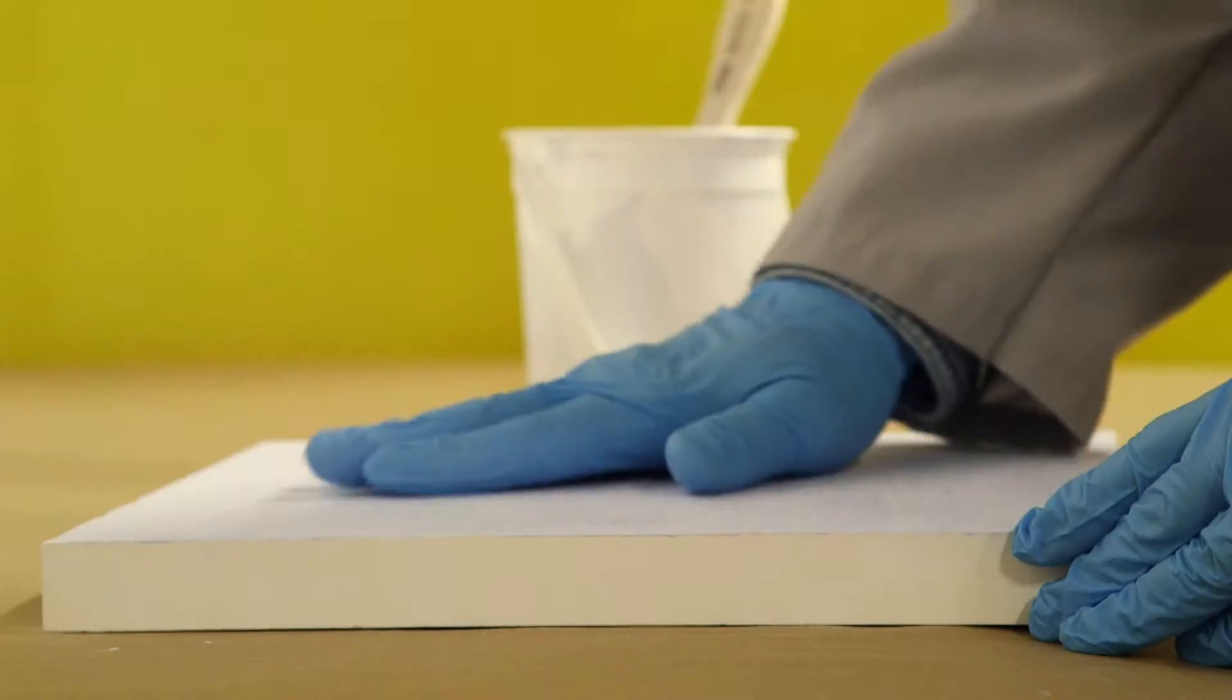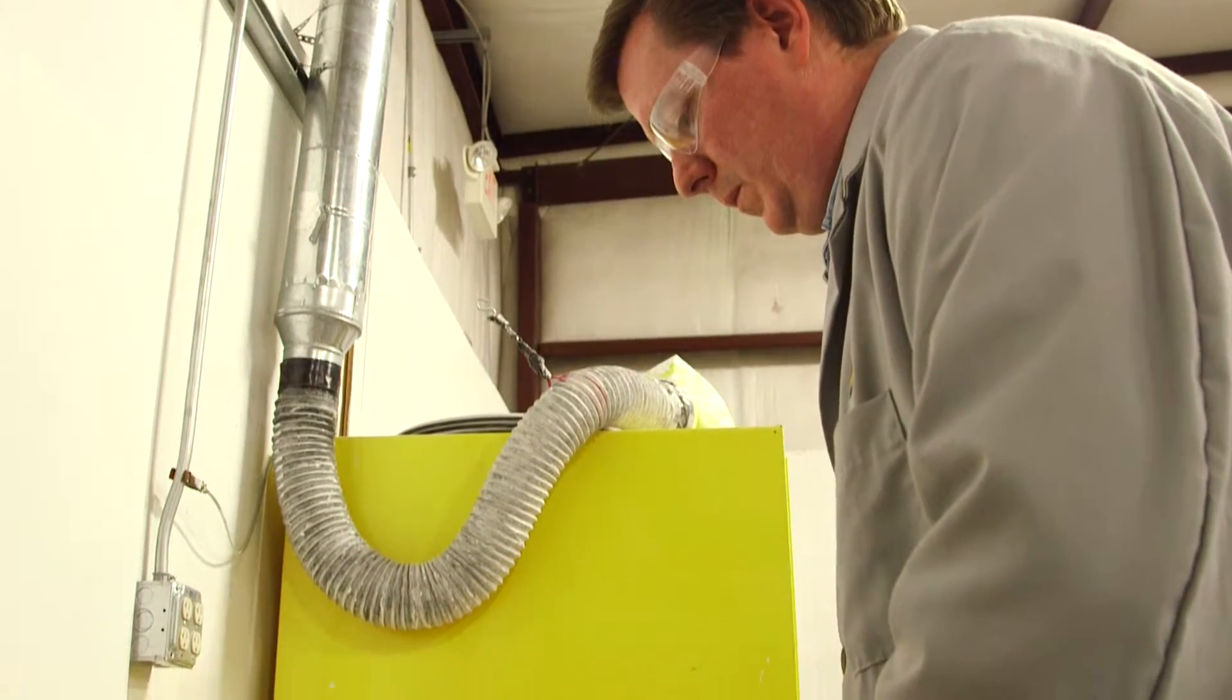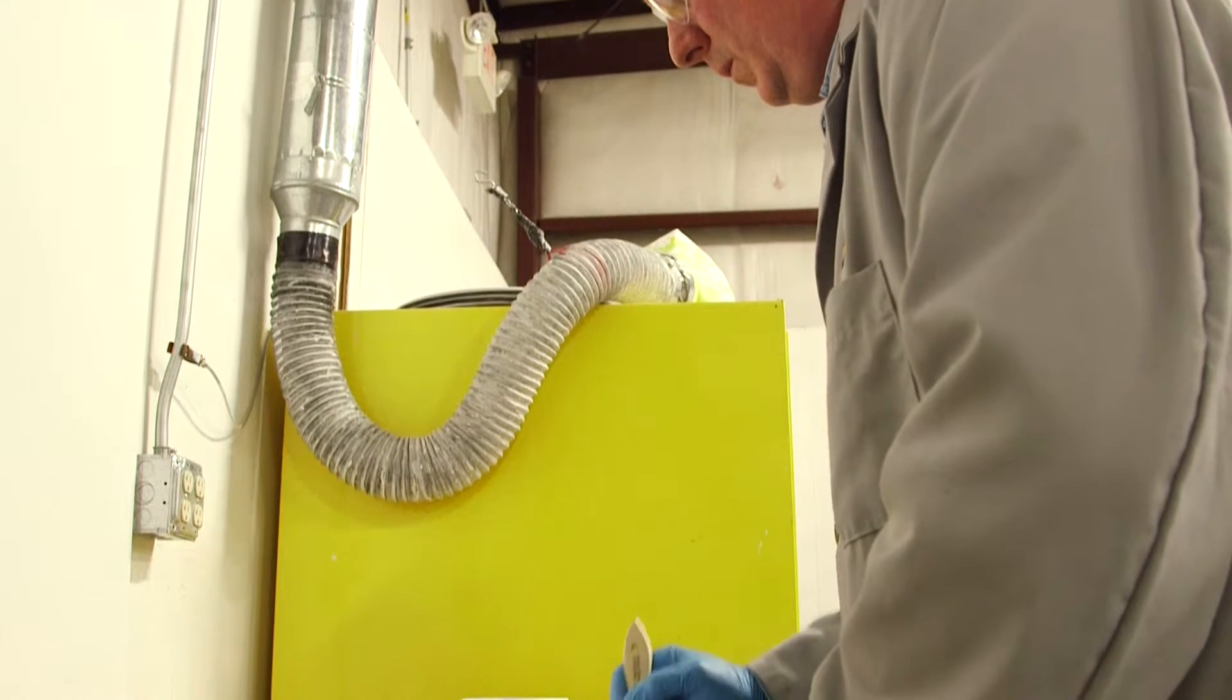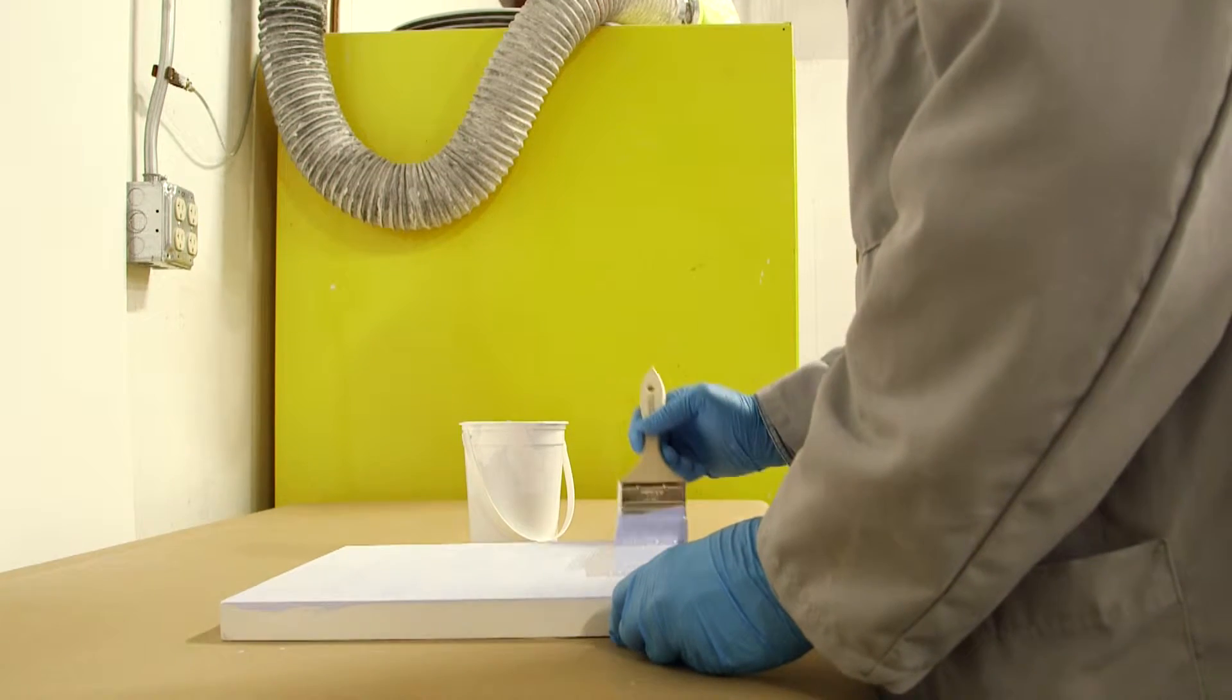The coating is then allowed to dry, dry to the touch. A single thin coating can have areas that are not too uniform. Sometimes, brushing onto a substrate heated to around 40 to 50°C, 100 to 125°F, can facilitate drying.